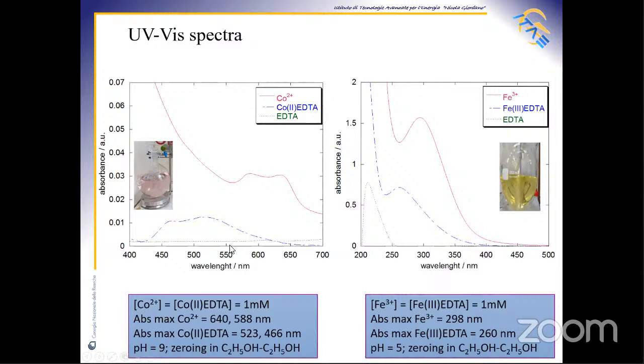To the left, it can be seen that EDTA does not absorb the visible light, whereas cobalt 2+ has two main peaks. In the case of cobalt EDTA, the two peaks shift towards lower wavelengths. That means the metal is completely chelated with the EDTA agent, as reported in the literature. Also in this case, hypsochromic and hypochromic effects are shown for the iron EDTA formation. These effects depend on the presence of functional groups close to the chromophore that decrease the electronic delocalization.